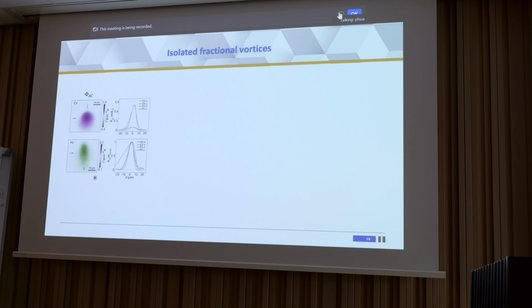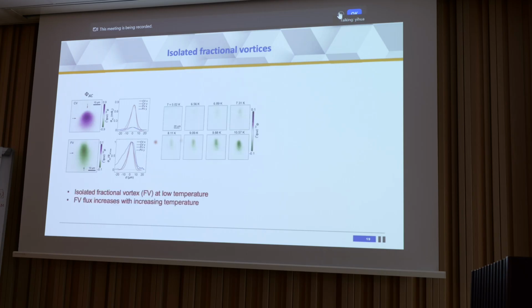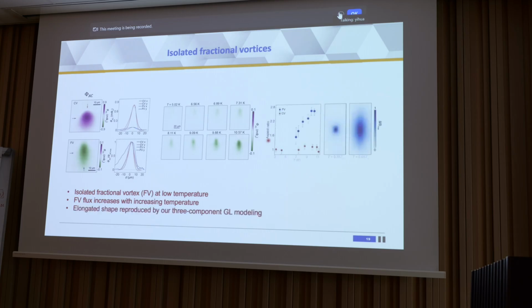Now, if we look at a conventional vortex and a fractional vortex at low temperature, we can immediately see that the AC flux signal can indeed detect a fractional vortex. However, its shape is quite different from a conventional vortex. Basically, it has a very elongated shape that's longer in the vertical direction. And as we increase the temperature, you can see that the fractional vortex has a stronger contrast, even increasing up to 10.57 Kelvin. And this is consistent with the three-component GL modeling done by Igor.